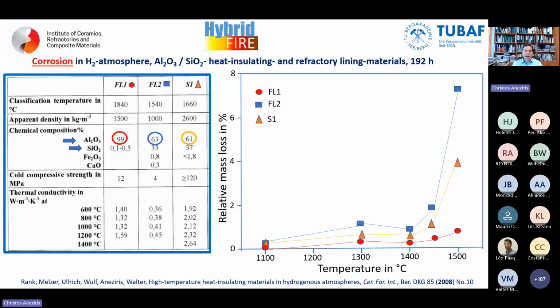Somebody would say alumina, yes. What happens if we have a little bit of silica? Because aluminum silicates are an approach to have improved thermal shock. We see the blue squares or the orange or yellow triangles. These are alumina silicate ceramics or insulating materials, and we see that we have a great negative impact.